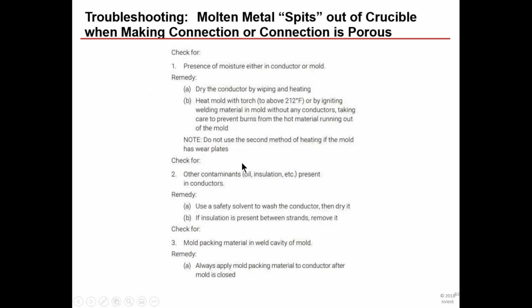Similar to what we've already talked about, molten metal spits out of the crucible when making a connection. Here's where it becomes a safety issue by not taking out the moisture. The moisture in the mold could actually cause it to spit the metal out of the crucible. Heat it up, dry it off, get any contaminants out of the way. Mold packing material, and so forth. And of course, just making sure your mold's in good condition.